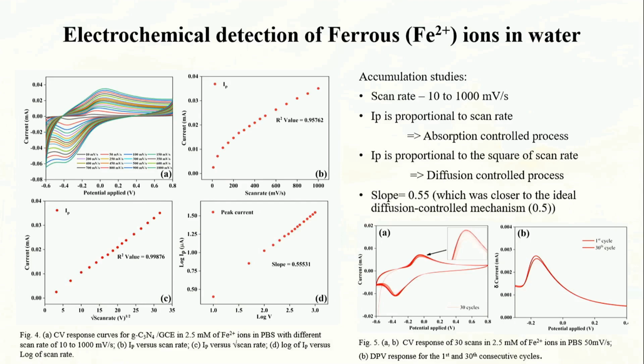We also did a repeatability test, running it for 30 cycles, and we looked at the changes between the first and the 30th cycle compared to the other concentration changes, for example from 2.5 millimolar to 3 millimolar. This is significantly less, so it's quite repeatable.